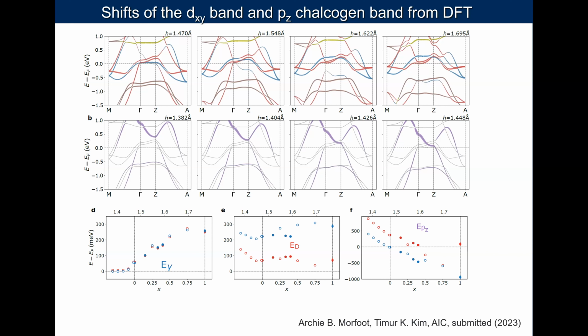You have similar effects with C-axis compression, or would this not be strong enough? So C-axis compression occurs when you put sulfur. Here we have expansion. So the C-axis gets larger when we add tellurium. So it's the opposite effect to that. So to bring the pz band down to the Fermi level to create these potential topological crossings, we need to increase the size, to separate the iron layer from the pnictogen.